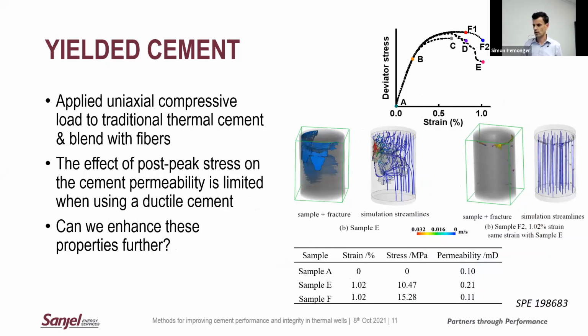And you're starting off at zero stress. This material has a permeability of 0.1 millidarcy. And if you take that material up to point E here on your stress strain curve, you've over doubled your permeability. And I think most people would have probably expected more, and we certainly expected to see more permeability change as well, considering the fact that this material had traditionally failed. But when you actually look at the micro CT analysis, you can see that you've got localized cracking, but that there aren't interconnected pathways of cracks.